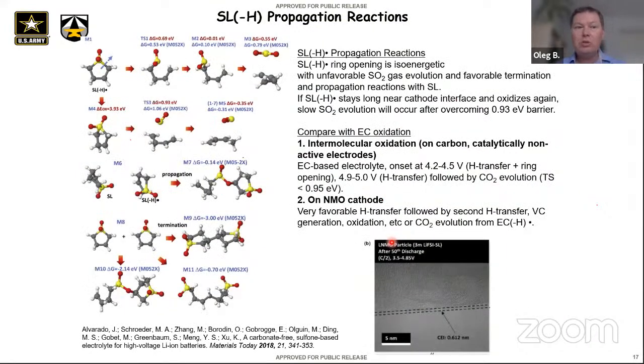To answer that question, we looked at what happens after that. In a very simple calculation, take a sulfolane with an abstracted hydrogen and try to open it up like I opened EC. There is a reasonable barrier, 0.7 eV, and this reaction is actually isoenergetic. So it's going to be a very small yield. Very small part will open the ring, and even if it opens, it doesn't want to evolve SO2 the same way CO2 was evolved. In fact, you can get SO2 out only if this radical sticks around long enough to lose another electron, to have a second oxidation, and then it will have a pretty high barrier, 0.9 eV, and yes, then you can lose it. So it's not the most favorable reaction.